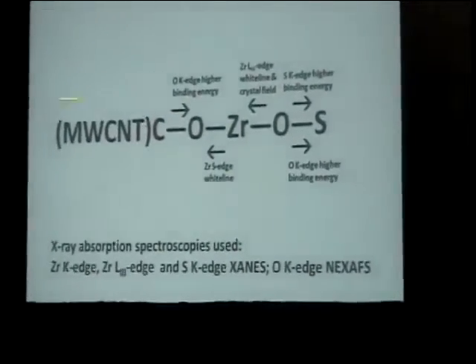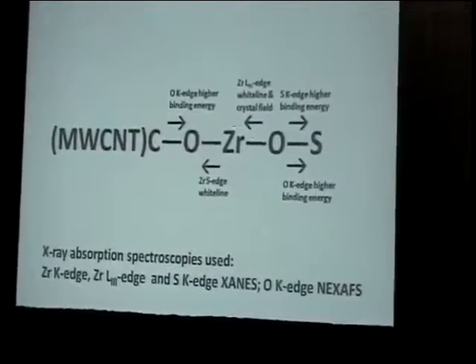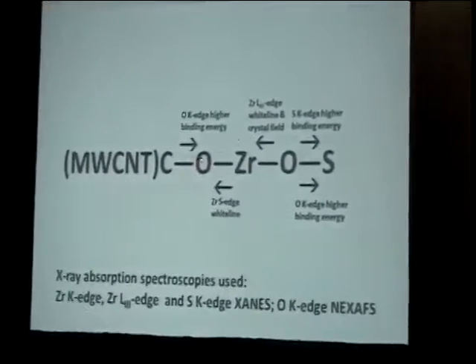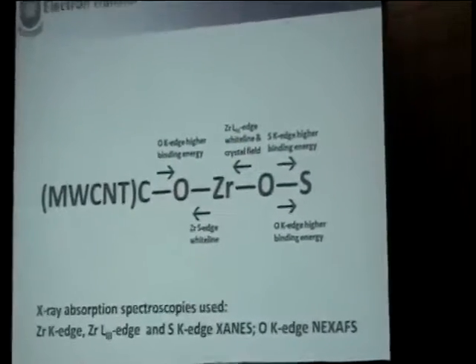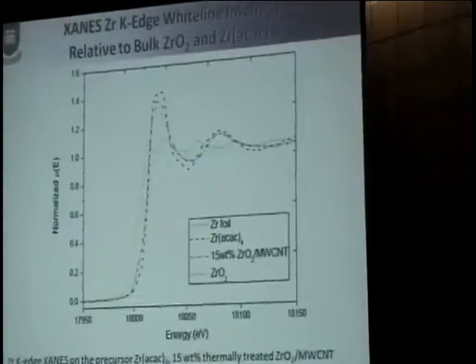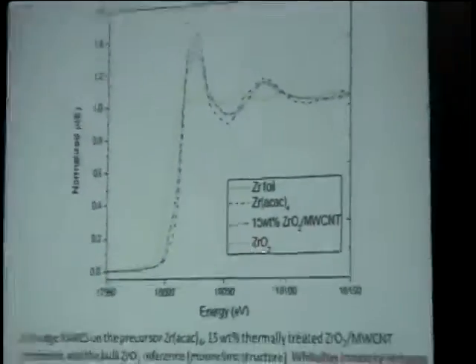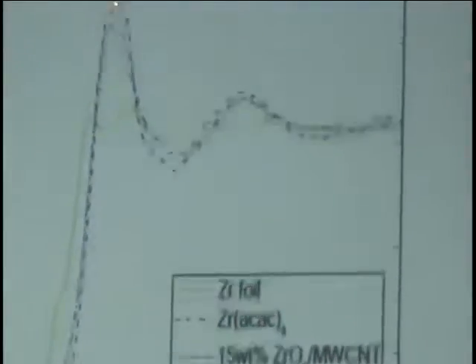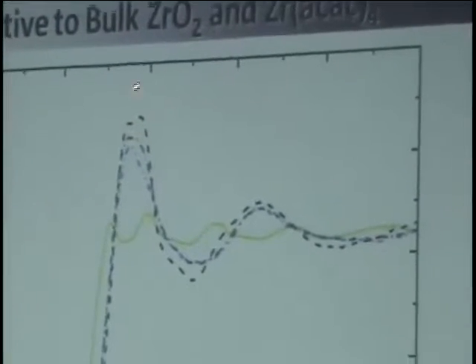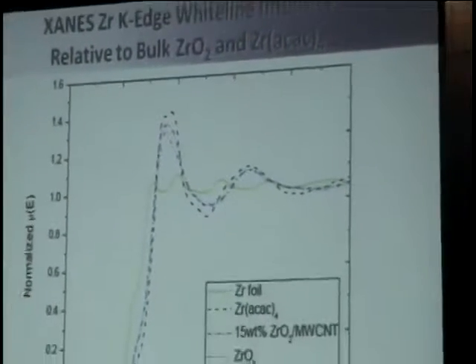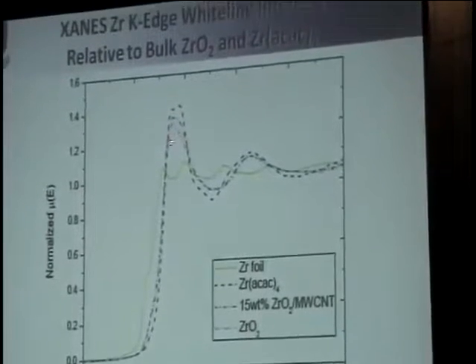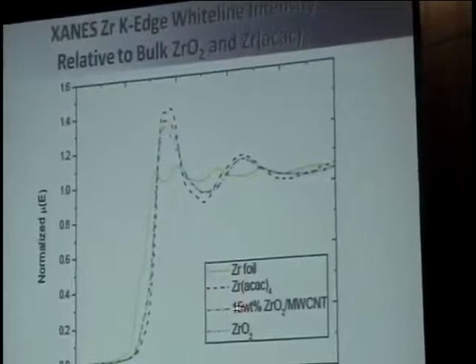It's carbon bonded to zirconium through oxygen, and then sulfur also being bonded to oxygen to zirconium. So here is the XANES at the K edge of zirconium, and there are several references here. The foil, which is not very useful. The other two are the precursor, the zirconium acetylacetonate, which has the highest white line intensity, and the zirconium dioxide, which has got the lowest of the oxides, and then in between them is our actual catalyst.